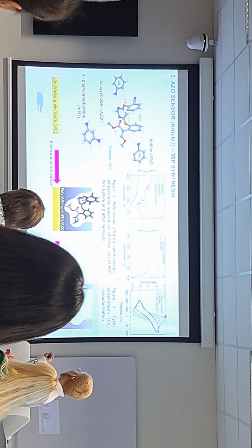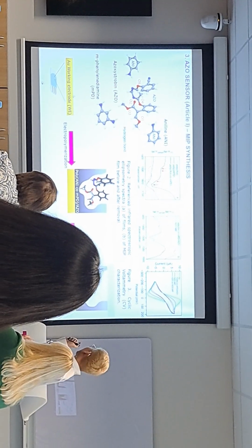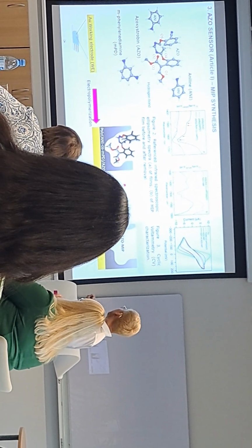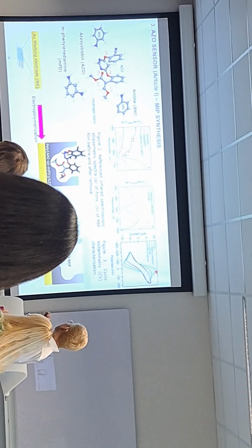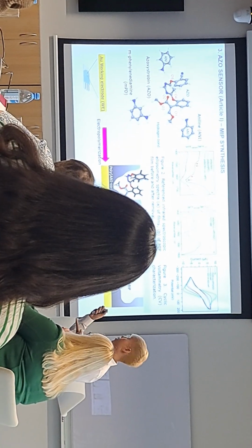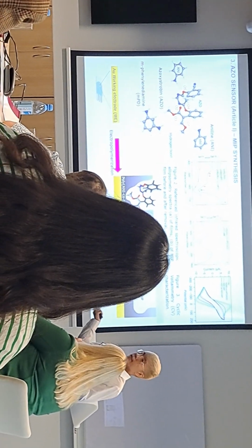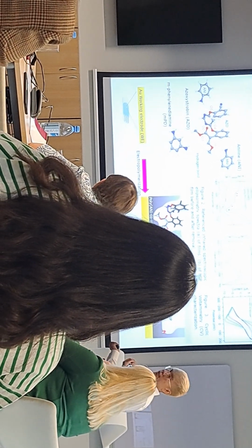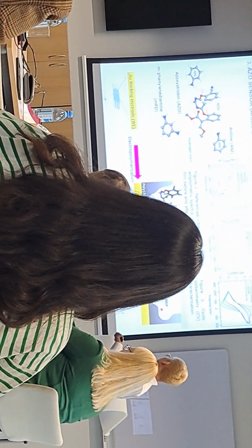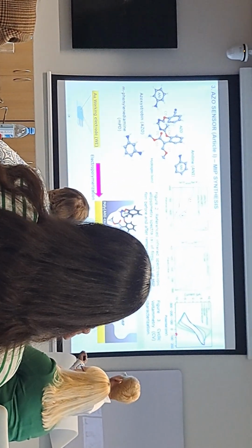The second characterization is cyclic voltammetry. So I have the yellow curve, it represents this, and since my polymer structure is non-conductive, after synthesizing this, I measure, I see the oxidation peak and the reduction peak become smaller. This means that some non-conductive material has formed, but after removal by acid, the peaks start to become higher. This indirectly tells me that some cavities inside here make it easy to measure the signal. And after that, with the red curve, I want to measure something in water. I put this one inside the water, and the molecule goes into here again, and the signal becomes smaller again. Everything starts to be logical here.